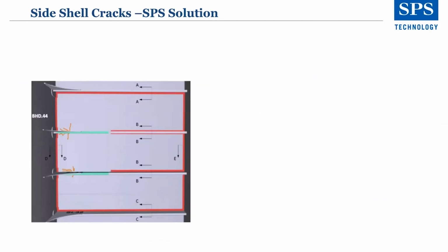After which, looking face on to the side shell from the inside, you can see over 3 bays is what we call it, where the cracks are identified with orange, and a section of the new stiffener has been removed as denoted by the green. So then we install SPS. We need to surface prepare the area back to 60 microns. So we prepare that and clean it.